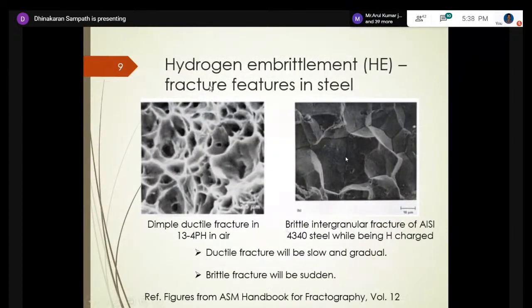So what do we see in the fracture surface? In A, we see dimple features like this arising from void coalescence. And in hydrogen, the crack runs through the grain boundary, and we can see the grains themselves with facets, so you are seeing the surface of the boundaries. And this is very brittle compared to this. That means the ductile fracture will be slow and gradual, but brittle fracture like this, intergranular fracture, will be very sudden. And yeah, it's without any hint.